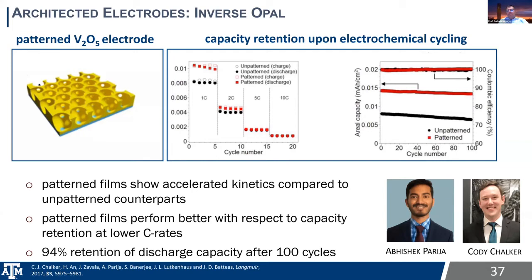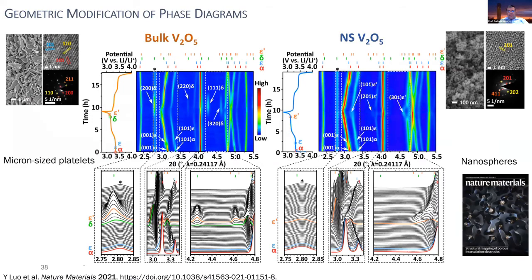So going back to what you could do in a real battery, again, this is work we just published, and what we can do is we can go to very small particle sizes, okay? So below 35 nanometers or so. And when we go to these small particle sizes, you can no longer stabilize phase boundaries in the system. And since you can no longer stabilize phase boundaries, you end up having single phase lithiation the entire way through, and you in fact stabilize a metastable form of lithium V2O5, and then you can take it out again and you can cycle it, and it's completely reversible.